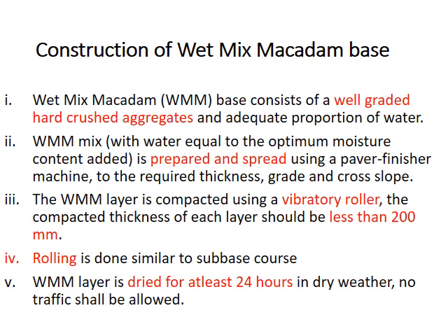Next, you have the base course. Wet mix macadam base course is common, and wet mix macadam consists of well graded hard crushed aggregates along with water. So the mix of aggregates and water is prepared and it is spread using a paver finisher machine to the required thickness, grade and cross slope, and then the layer is compacted using a vibratory roller.